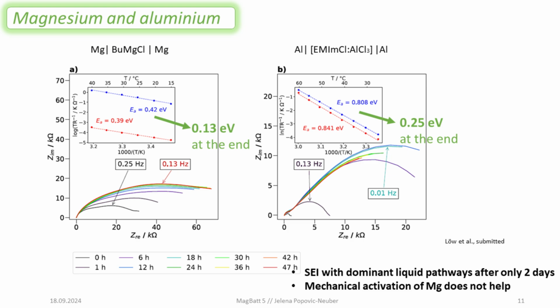And what we see, as we typically see in magnesium, is this really high resistances of the interfaces. So this looks quite horrible. It's every electrochemist's nightmare. In particular, if you do a lot of impedance spectroscopy, you see a lot of features happening here. So it's not this beautiful one semicircle with a very nicely defined capacity, right? So it tends to be more complicated than that. So in this paper, we also try to elucidate a little bit of these kind of features in impedance, but I'm not going to bother you too much about it because it's very nerdy impedance stuff.